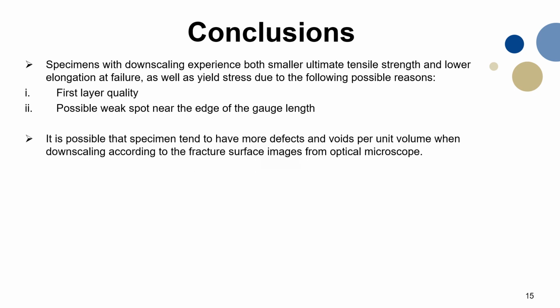And third, it is possible that specimens tend to have more defects and voids per volume when downscaling, according to the fracture image from the optical microscope. We haven't done a true defect analysis with the microscope, but this is the hypothesis we have.